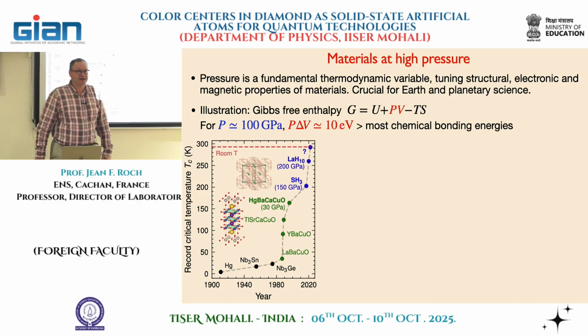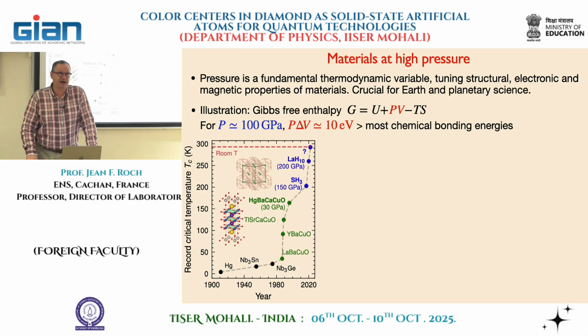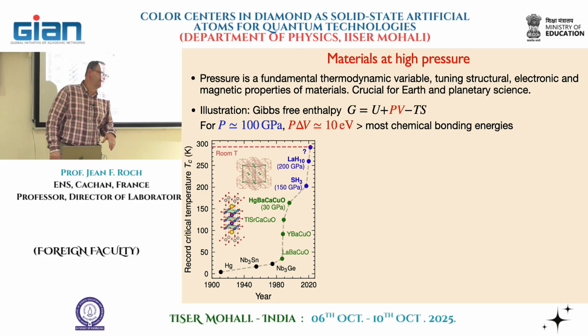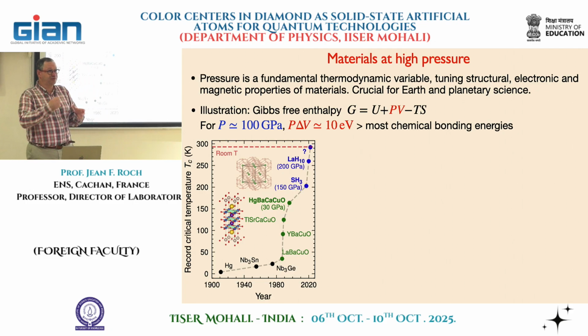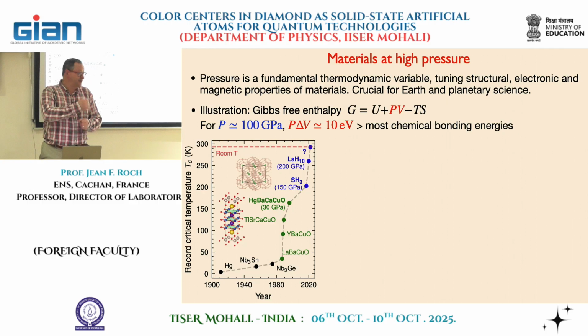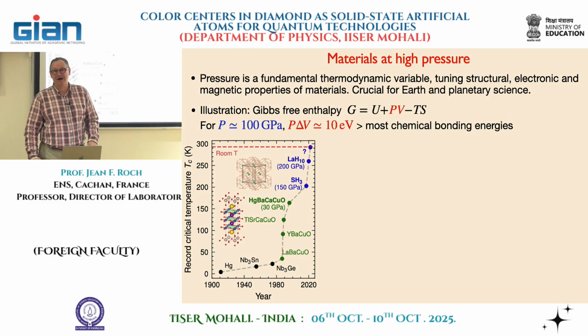YBaCuO is superconducting at a temperature above liquid nitrogen, and that's why we can do a lot of demo experiments using this material very easily. It's also easy to produce. Basically, if you have an oven, you take the different samples that you have here, you crush them with a pestle, and then you cook it for a while, and you get your YBaCuO sample.